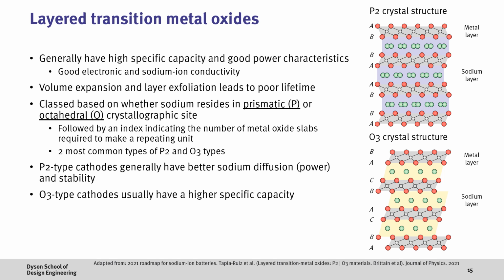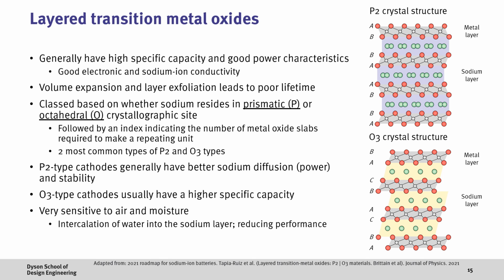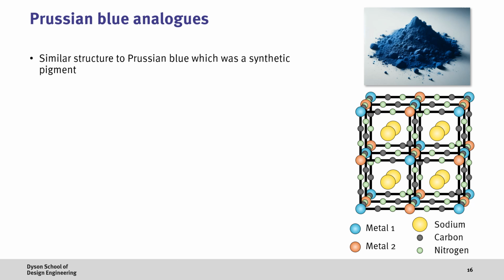Whilst exact properties vary, P2 type cathodes generally have better power and stability, and O3 type cathodes generally have higher specific capacity. However, a problem with this class of material is that they tend to be air and moisture sensitive, with water inserting into the sodium layers reducing performance. Next, with Prussian blue analogues, these materials have a similar crystal structure to Prussian blue synthetic pigments.